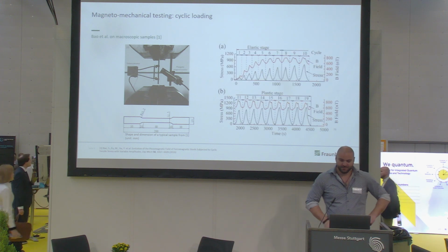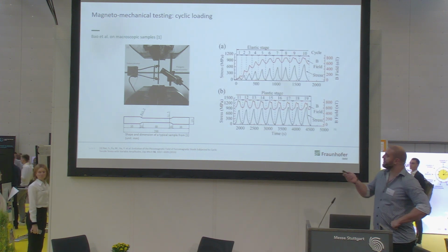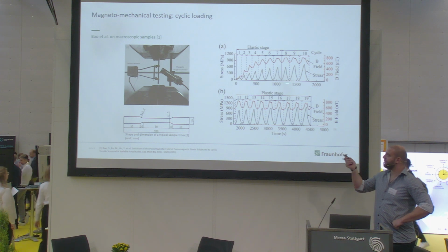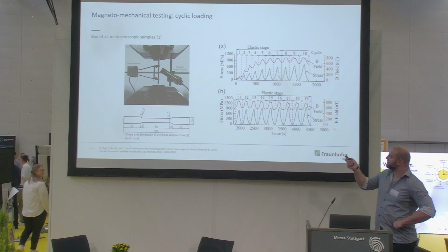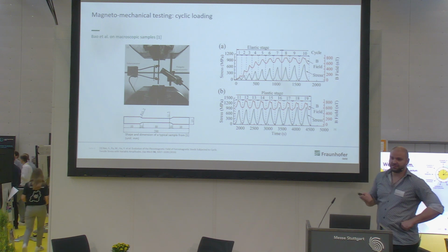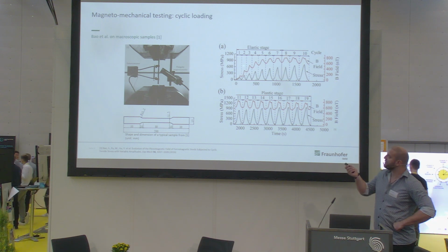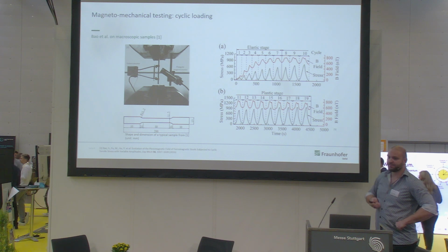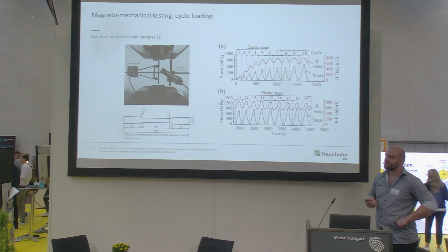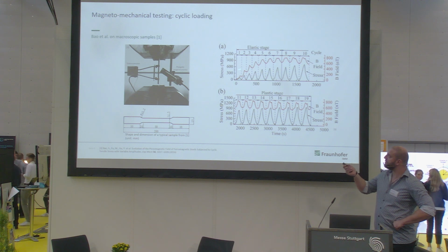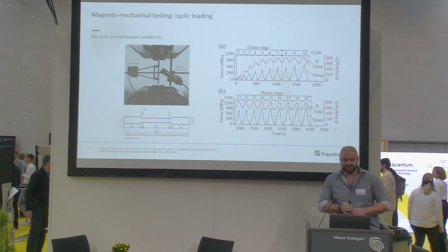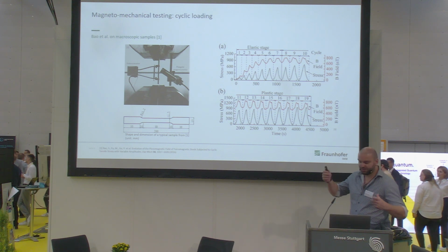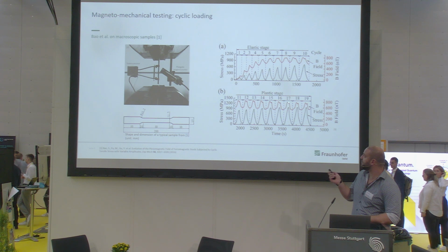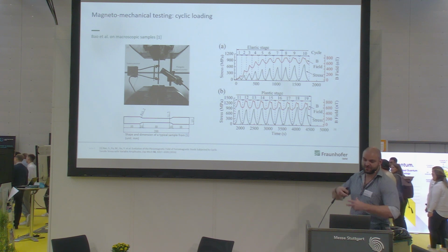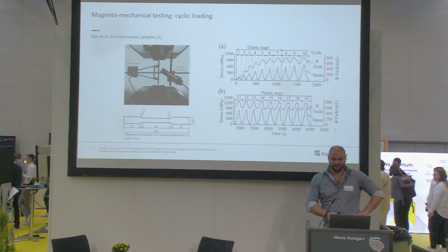So what do they see? If you look at this graph, you can see in black the stress over the number of loading cycles, which follows this certain pattern. And in red, you can see the magnetic field that is measured along. So the magnetic field really follows the stress cycles. Now there are certain things that we can see. First of all, we have a rise of the magnetic field in the beginning, and at a certain point you have these dents that are evolving on top of these stress amplitudes. This is called a Villari reversal, and this is a very typical effect when the strain that you apply becomes dominant in the end.